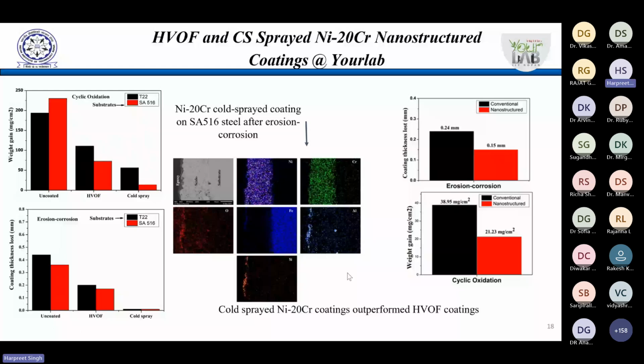Another thing which we did here was that we even compared how our cold spray process is placed with the high velocity oxy-fuel process, right? And we see here clearly that our nickel chromium coatings developed by the cold spray process were better than this one.